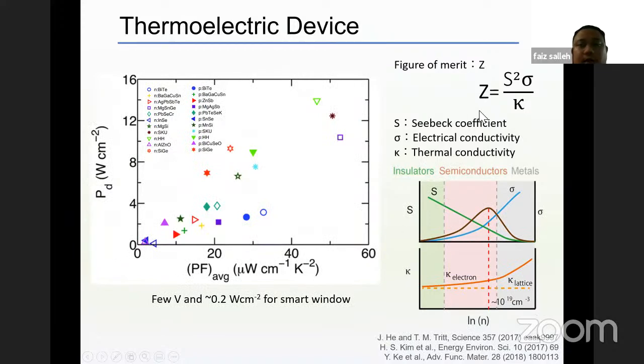And then if we look at this figure of merit, we can see the upper part, the Seebeck coefficient to the power of 2 multiplied by the electrical conductivity. We call it the power factor, or the thermoelectric power factor. And the bottom part is the thermal conductivity. This graph shows the relation between the power output as a function of the thermoelectric power factor. So we can see here that we need to improve the thermoelectric power factor. For example, the half-Heusler material can have a high power factor and high power output density.